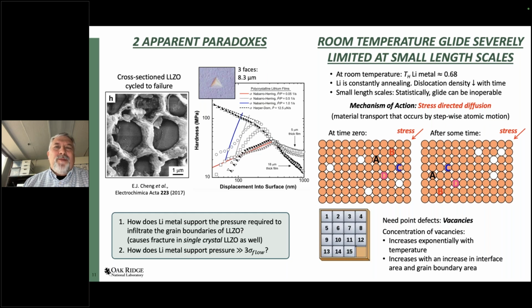At room temperature, we're at about 68% of lithium's absolute melting point. That means even at room temperature, the lithium is constantly annealing, so the dislocation density is just decreasing with time. At these relatively small length scales, the self-limiting behavior of lithium just becomes a statistical mechanics problem. It's all about the probability of finding or not finding the mobile dislocations or the active dislocation multiplication sources within these small constrained volumes of lithium metal.